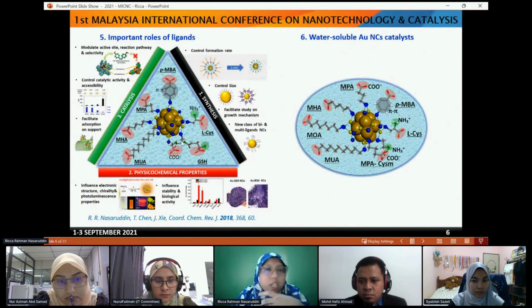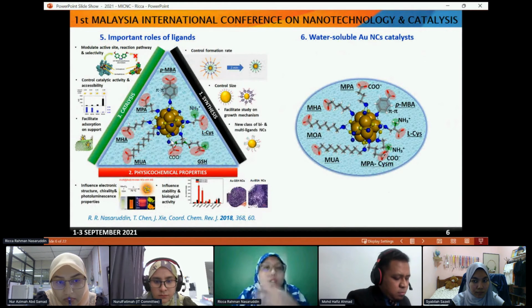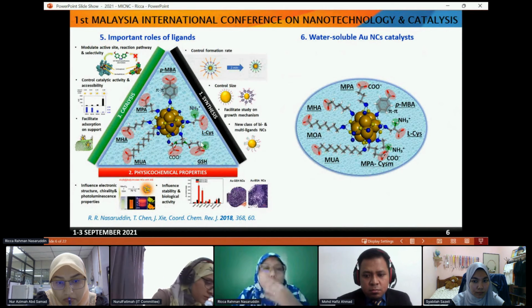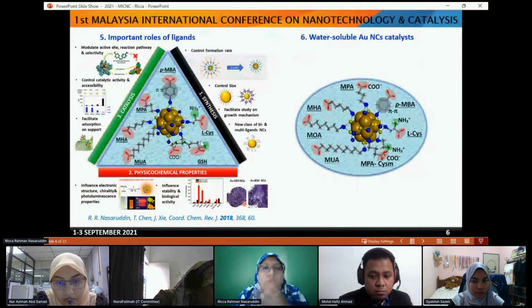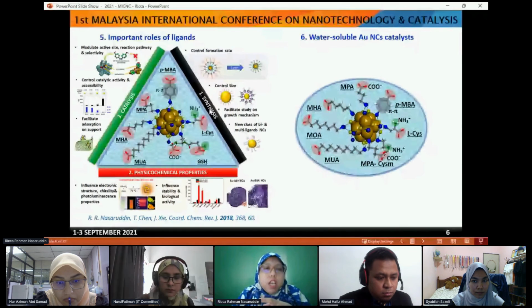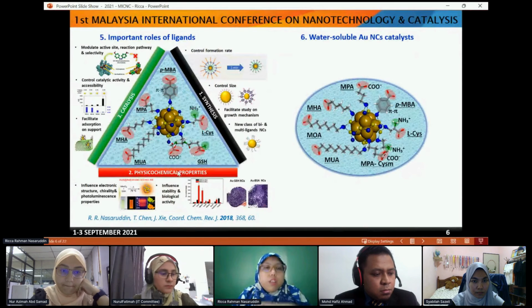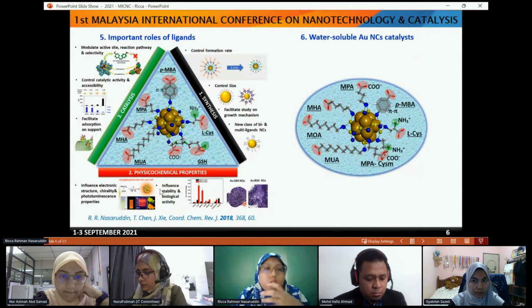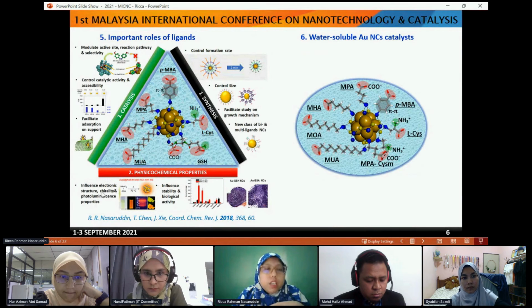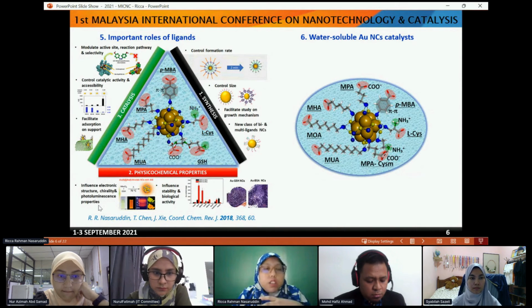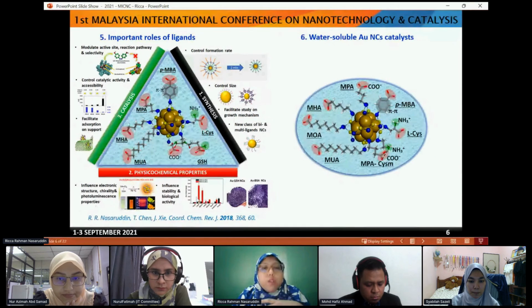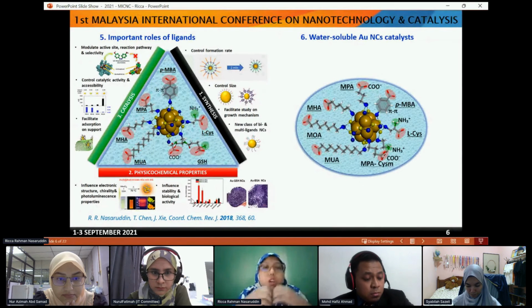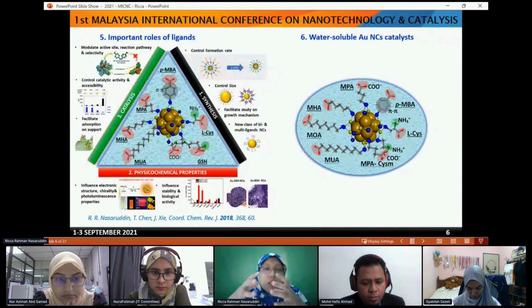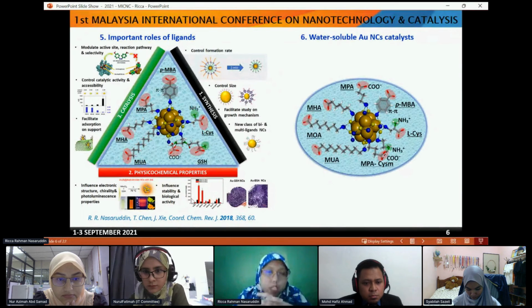For example, you change the ligand, you do something to the ligand, you add more ligand, not only one ligand, you can have bi-ligands. So you can understand the effects of this ligand on the synthesis process. And not only that, the ligands can also affect the physicochemical properties of your gold nanocluster, in terms of the chirality, the electronic structure, photoluminescent properties, and also biological activity. So it can be used to tailor your gold nanocluster for your specific reaction or your specific application.